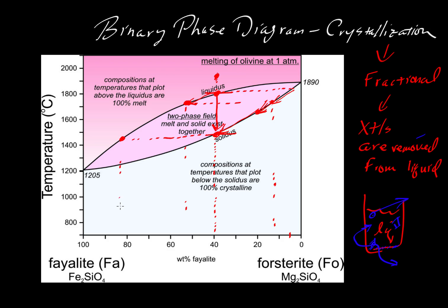The last little bit of liquid would be at about here. It looks like it would be at a little bit more iron-rich than FA80, maybe FA fayalite 82 or 83, something like that, at a little above 1400 degrees. But the amount of that liquid is infinitesimally small. As that liquid vanishes, the system becomes completely solid. But that's the case for equilibrium, where the crystals sit around and equilibrate with the liquid. So this cup simply fills up with crystalline material.